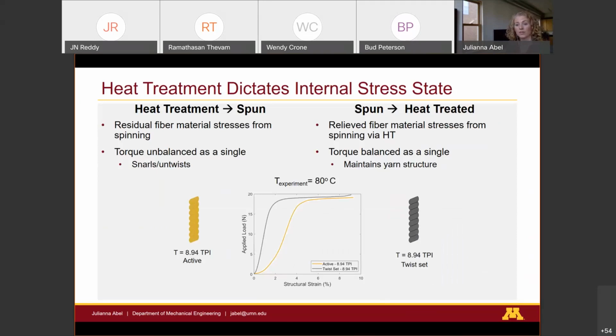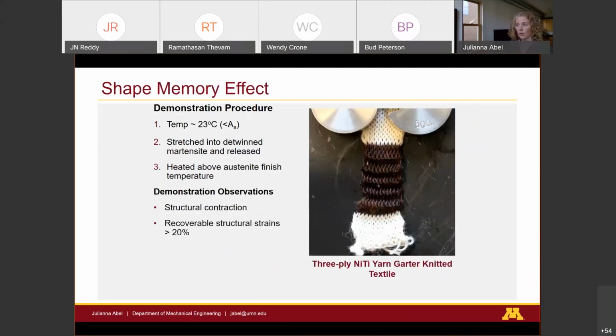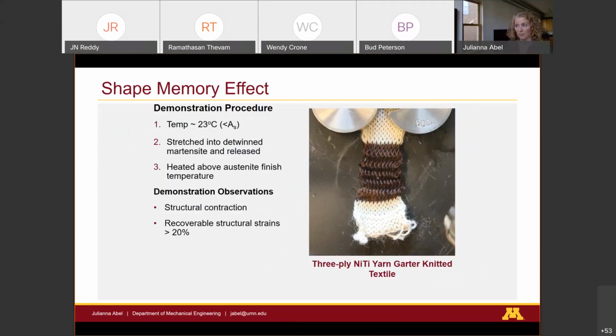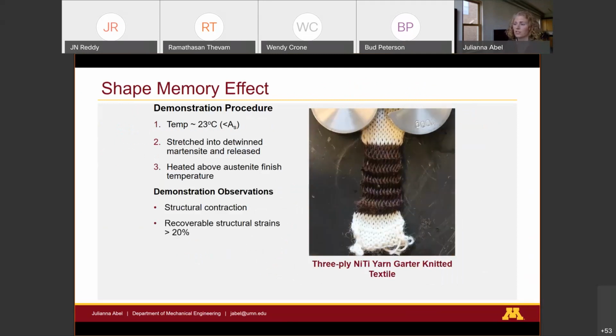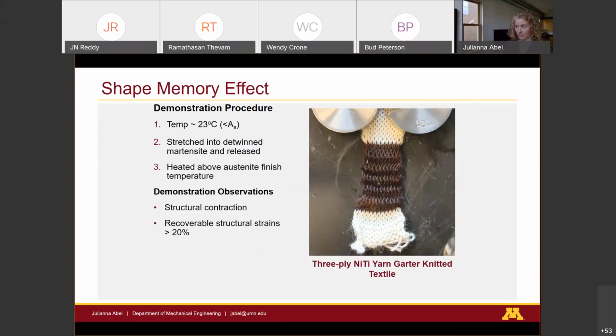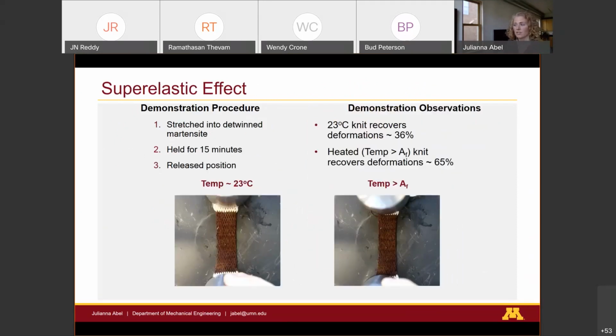And so through this heat treatment process is another knob that we can tune to create the mechanical performance that we want. So we'll go from the yarn into a structure, and this is 100% nitinol, all these fine nitinol wires in the black, and this is using the shape memory effect. So it's a 3-ply knitted garter structure, and as we heat it up, we see we're recovering those deformations just like we saw in the monofilament knitted structures. And we also see the shape memory effect.